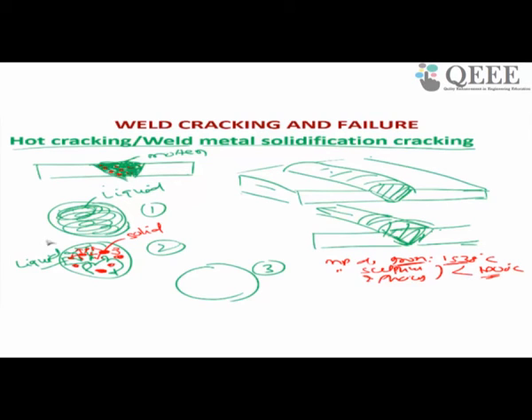After some time, these solid crystals will grow, and in the remaining area you will still have liquid. This liquid will again reject, since only when it comes near the melting point of sulfur and phosphorus will they solidify. As long as the temperature is higher than their melting point, only the iron solid crystals will form, and sulfur and phosphorus will still be in liquid state. So it will push sulfur and phosphorus away.